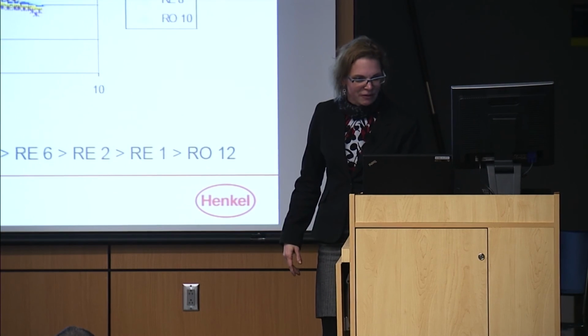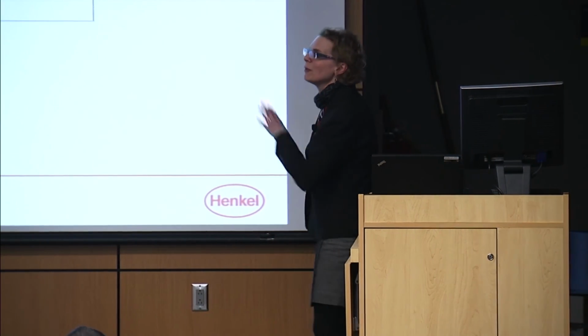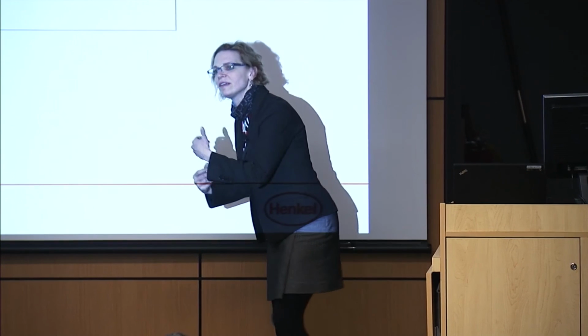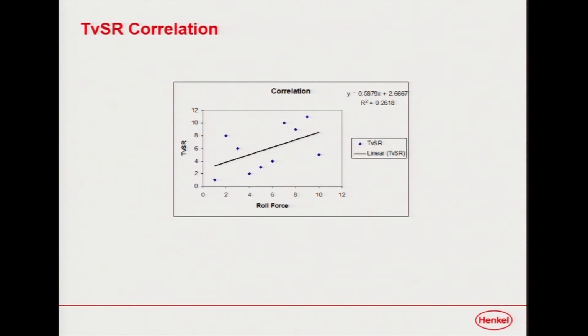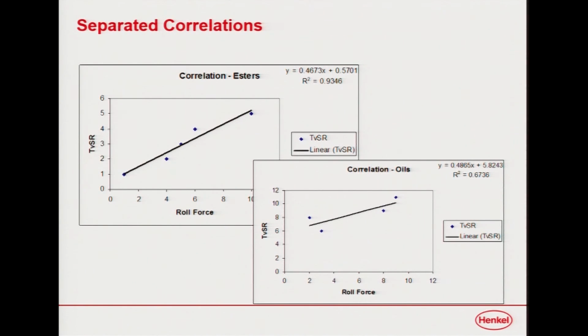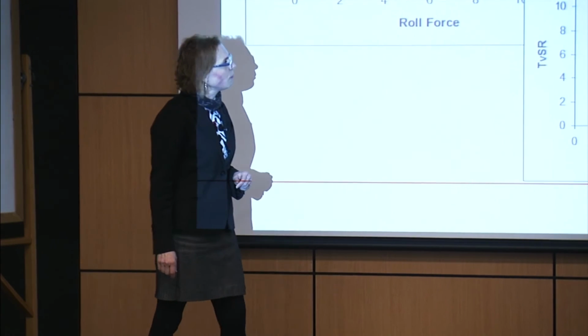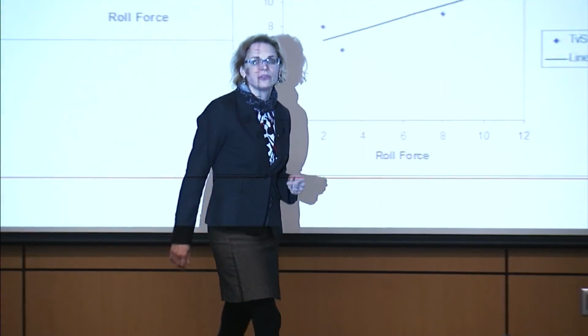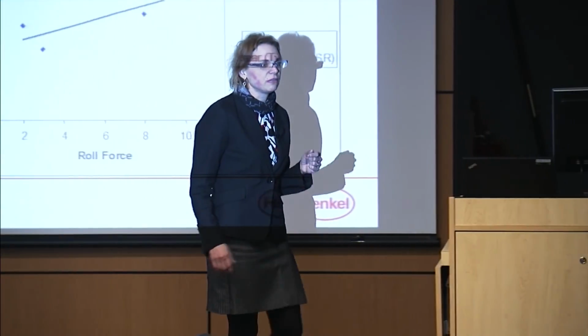So we did some other stuff. And what we found in the end was we went back to our rolling oils, and we did those same kind of tests on the rolling oils. And when we first did the correlation, it didn't look too good. So we split it out, and we said, well, what if the base oils are part of it? So the things that have paraffinic base oils, which are over here, so these more less chemically active base oils, versus those that were esters, which are relatively chemically active, and all of a sudden those correlations improved dramatically.